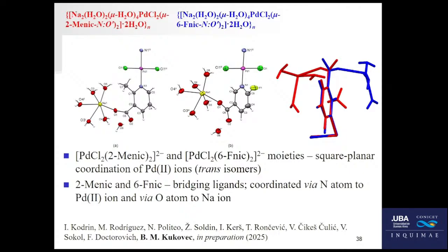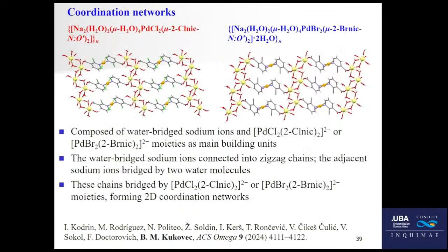In the case of the methyl, this one is the 2-methylnicotinate polymer and the 6-fluoronicotinate polymer. They are more or less very similar to the previous one. I'm not going to mention it, but in this case you can see they don't overlap that nicely because of this part, the sodium coordinated with water again. These two do not overlap in the methyl and fluoronicotinate compounds. So how do these 2D networks look? You can see it here. This is, as it says here, the 2-chloronicotinic polymer, and this one is the 2-bromonicotinic polymer.